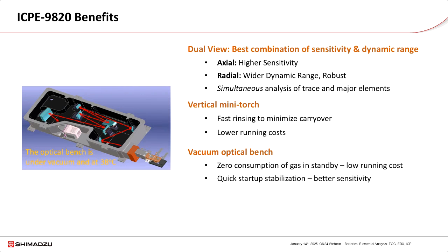Unlike other ICP-OES systems in the market that need constant purge of the optical bench, Shimadzu ICPE-9820 is equipped with a vacuum pump that can run 24/7 to keep the optical bench under vacuum, which means zero consumption of gas in standby and therefore lower running cost. The optical bench is also kept at about 38 degrees C, constant vacuum, constant temperature. This enables quick startup of the instrument with better stabilization and better sensitivity.